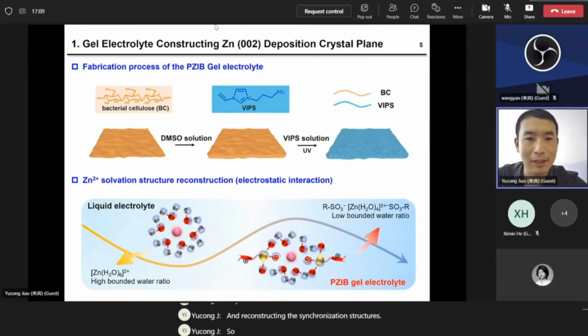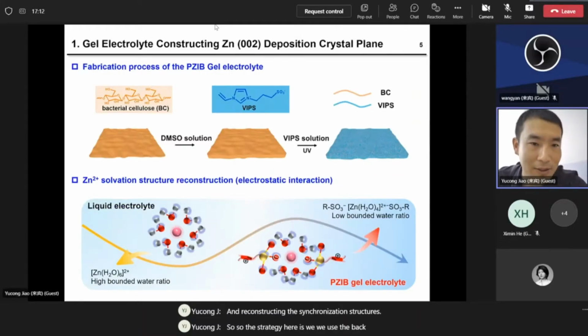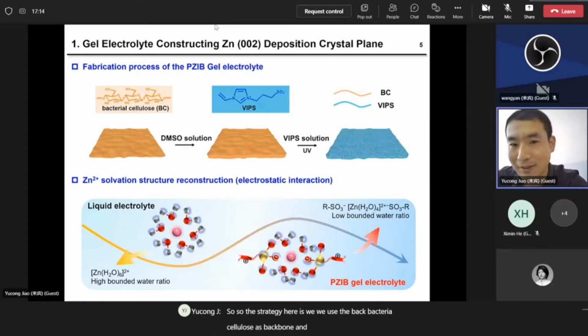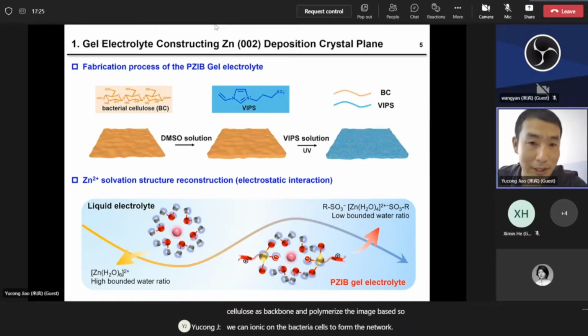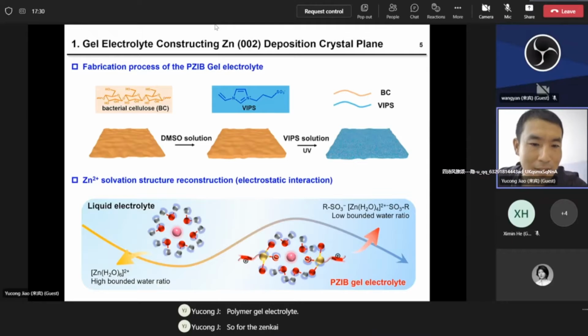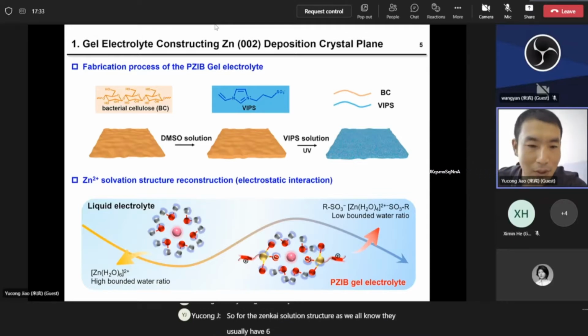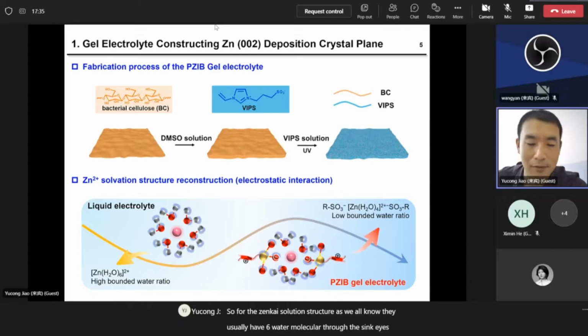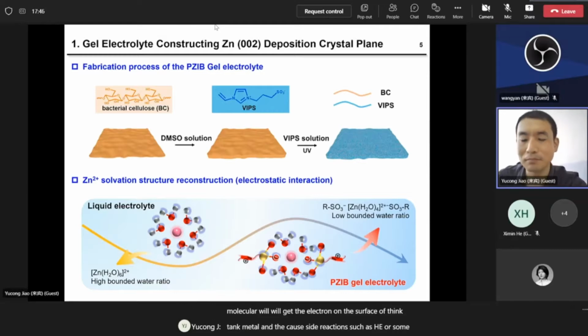So the strategy here is we use the bacteria cellulose as backbone and polymerize the imidazole-based weak ionic on the bacteria cellulose to form the dual network polymer gel electrolyte. So for the zinc ion solution structure, we know they usually have 6 water molecules around the zinc ions. This molecule will get the electron on the surface of zinc metal and cause side reactions such as HER or some other side reactions.